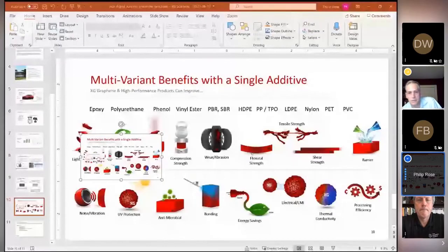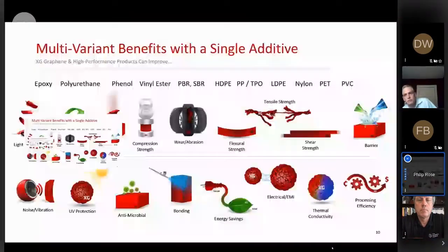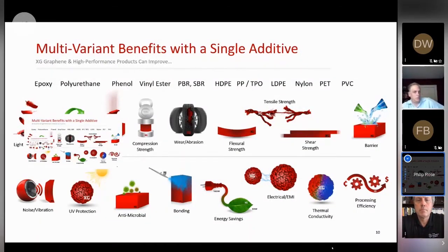Sure. Really, this slide is intended to indicate the range of performance benefits one could achieve using graphene nanoplatelets. The applications themselves are basically endless. We have certain coating customers that will leverage the barrier properties, but also the thermal management properties, where if you put graphene nanoplatelets into a primer coating, for example, you can get the heat to normalize and spread out over the surface of the coating, get very good coating uniformity to improve optical appearance, for example. You can also perhaps get electrostatic dissipation performance if you had an application where you wanted to replace, I don't know, nickel on the inside lining of a gas filler tube, for example. So it's really being able to leverage the multiple performance attributes that begins to excite the imagination.